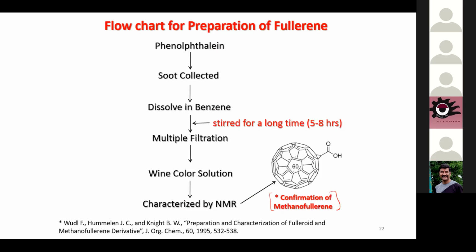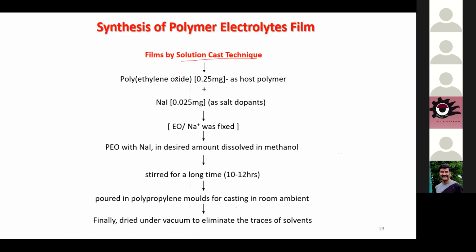And for synthesis of the polymer electrolyte, a very standard solution technique we have used to develop thin polymer films. We have used polyethylene oxide 0.25 gram as a host polymer and 10% of the NaI, 0.025 gram of salt, we have adopted. And the ratio was fixed, and PEO with NaI in the desired amount was dissolved in methanol, and we stirred it for some time. After getting it, we added the so prepared fullerene solution and stirred for a long time, 10 to 12 hours. And when we got the viscous solution, we poured it into the polypropylene petri dish, and we got the thin film of the order of 200 to 300 microns.